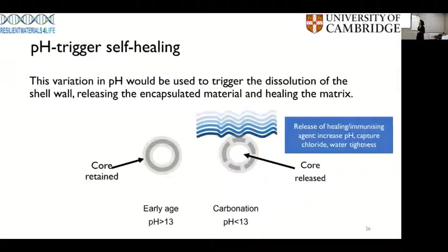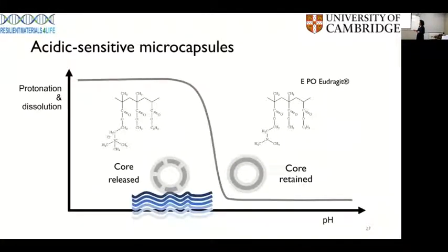I also investigated microfluidics to produce capsules that are pH triggered, by putting a pH sensitive chemical inside of that acrylic shell that will then be triggered by a change in the pH. So that's the idea: when we have an alkaline pH, we have the retention of the core, and then the core would release when the pH is decreasing. That's very challenging. Any of you know why?